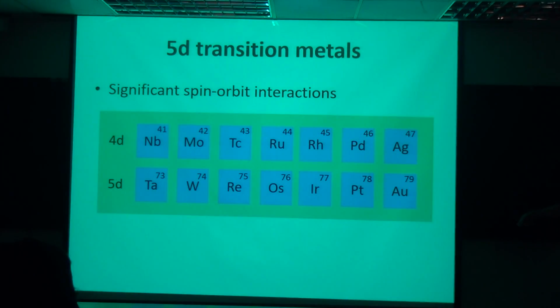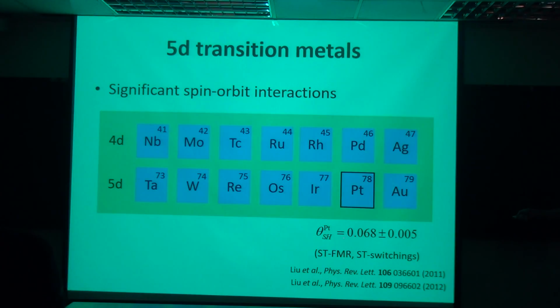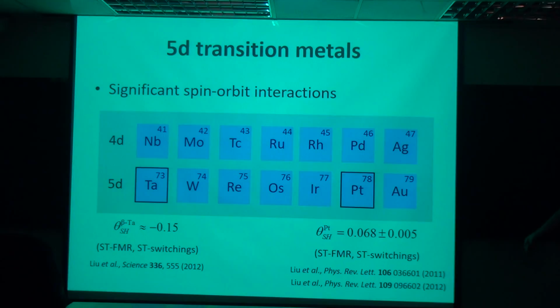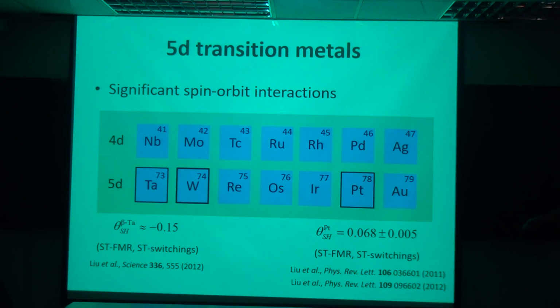And you know, since we know that platinum has a spin-Hall angle of about 7%, and we also know that for tantalum it's minus 15, a natural question to ask is whether or not there is another material with an even larger spin-Hall angle. So at that time, almost at the same time when we got the result from tantalum, I moved on to tungsten, because I know that tungsten is right next to tantalum, and at the same time it's much cheaper than this, and this, and this. So it seems to be a reasonable approach. So just work on tungsten.